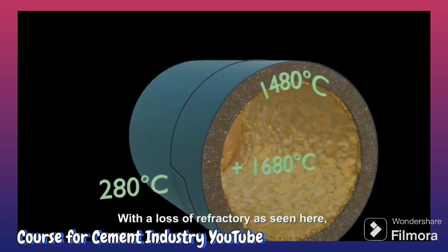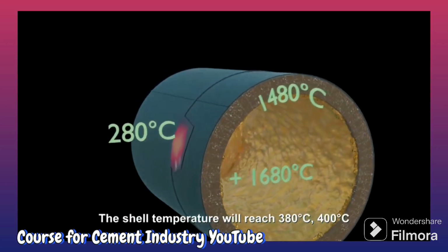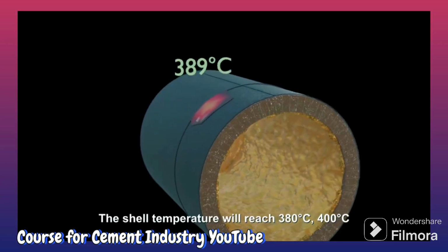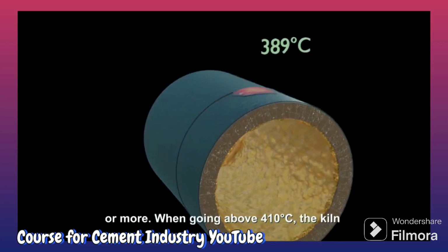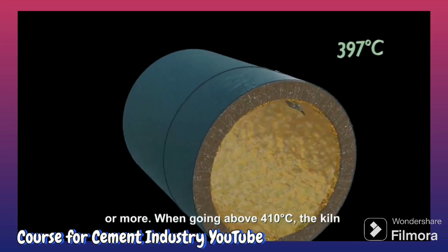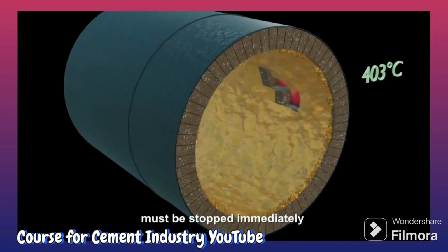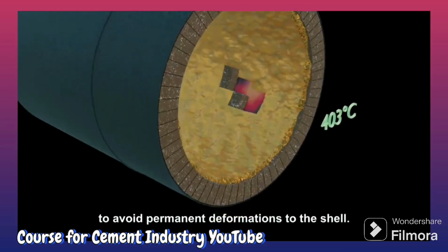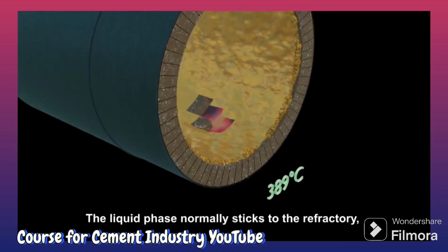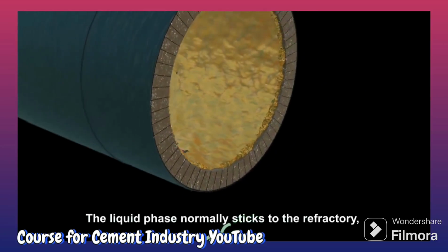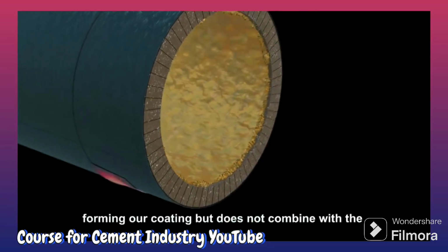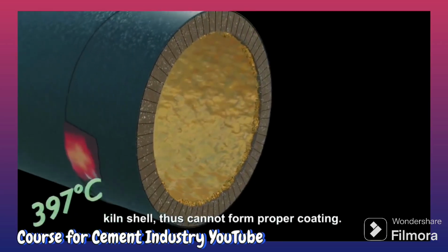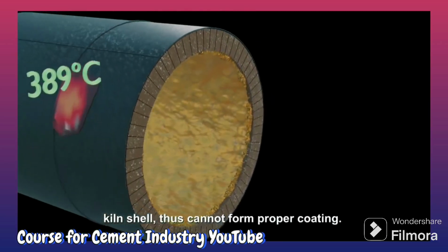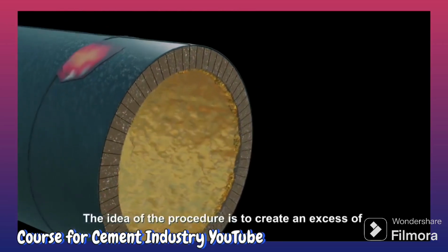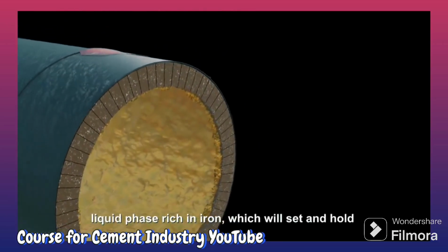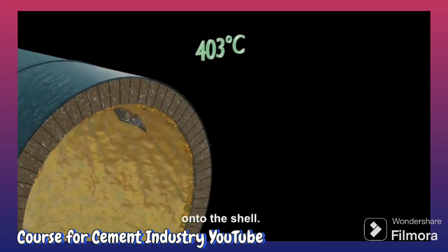With a loss of refractory as seen here, the shell temperature will reach 380–400 degrees Celsius or more. When going above 410 degrees Celsius, the kiln must be stopped immediately to avoid permanent deformations to the shell. The liquid phase normally sticks to the refractory, forming our coating, but does not combine with the kiln shell, thus cannot form proper coating. The idea of the procedure is to create an excess of liquid phase rich in iron, which will set and hold onto the shell.